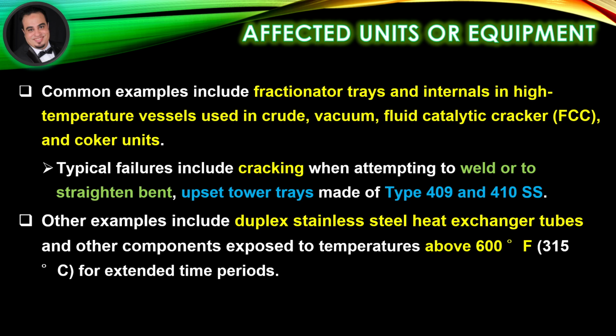Other examples include duplex stainless steel heat exchanger tubes, and other components exposed to temperatures above 600 degrees Fahrenheit for extended time periods. Please note that duplex stainless steels are normally limited to a maximum service temperature of 600 degrees Fahrenheit.